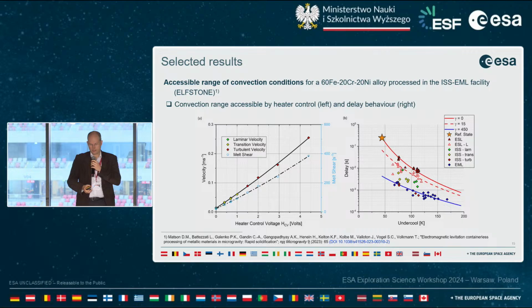The next example is the iron-chromium-nickel alloys. I touched upon the delay time issue yesterday if you followed the presentation. This is very much related to a corresponding US project, Elfstone. What is shown here is solidification velocity as a function of heater control voltage on the left-hand side. Heater control voltage corresponds to fluid flow inside the sample. So the higher the control voltage of the heater, the more fluid flow you have in the sample. And what you see here is that the solidification velocity is increasing with increasing fluid flow.